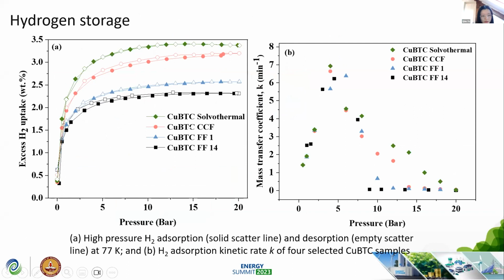As you can see, we choose 3 samples from the ball milling from the DOE results. The first one is this one. It has the highest crystal size, and then is the copper BTC FF1 is the center point of the synthesis, and this one, the copper BTC FF14, has the smallest crystal size. In addition, we also include the copper BTC from the solvothermal synthesis. This is regarded as the benchmark in our research.